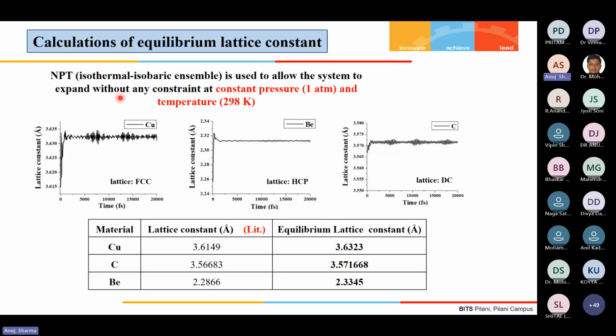And after that, the lattice constants were evaluated. So usually, for creating the structure in the simulation, I took the lattice constants from the literature for copper, carbon, and beryllium. But in the literature, these constants are given at different temperatures. I am carrying out my simulation at 298 or 293 Kelvin, so I first have to find out these lattice constants at this temperature, because the literature values are not valid at that temperature.